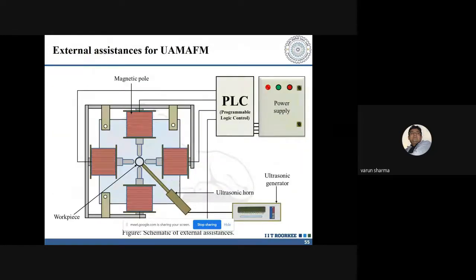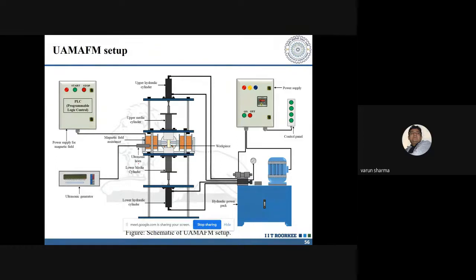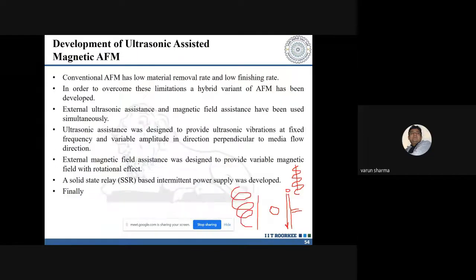So we used an intermittent operation. There were 4 magnetic poles, and those magnetic poles were switched from one end to the other. So when one is active, the others are stopped, and your abrasive particles start moving in a circular manner. This is the schematic of that process, and we are in the process of finishing certain titanium and nickel based alloys using this kind of setup.